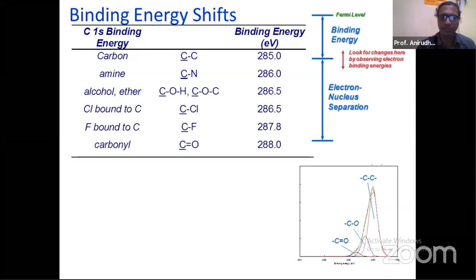The point to be noted is that this new formation is likely to affect the electron energy levels of the electron fields around each and every nucleus, and so they change to a new value because of this bonding. Now when you are trying to find the binding energy of a 1s electron, for example in carbon, in unbonded form it has a value of 285.0, but when it has bonded with chlorine, these electron energy levels are all different; they have changed.